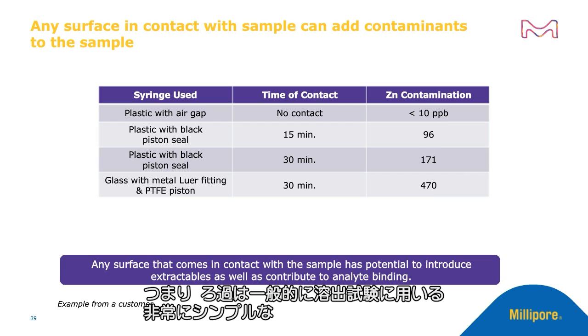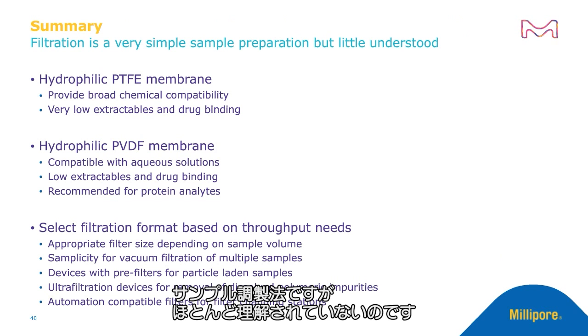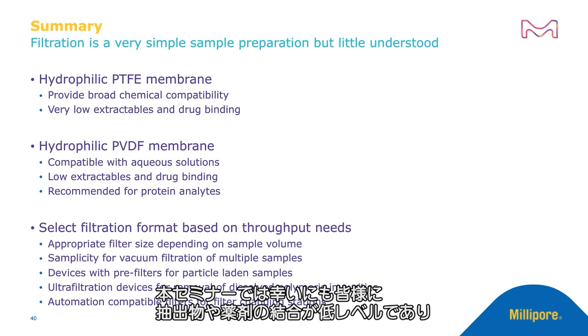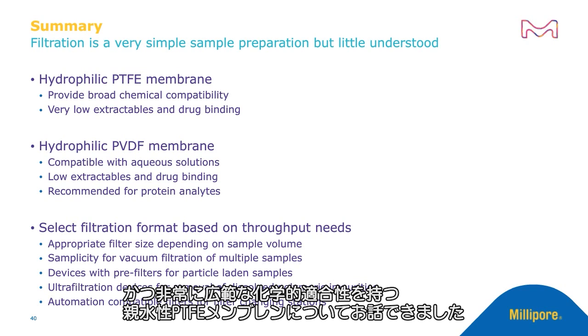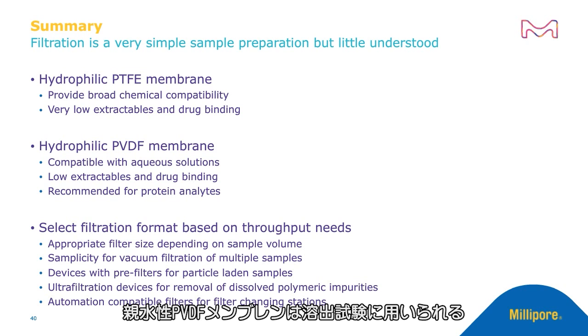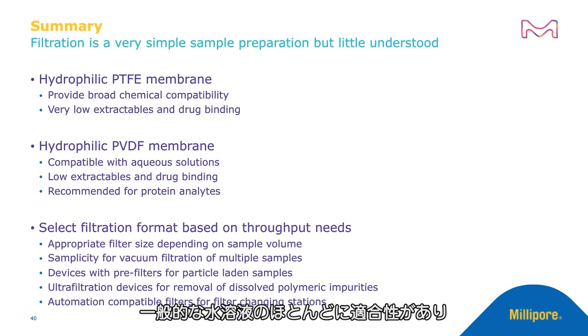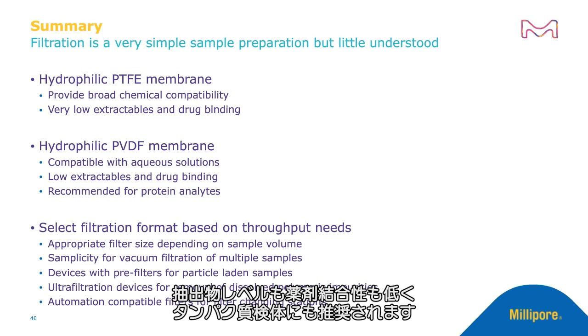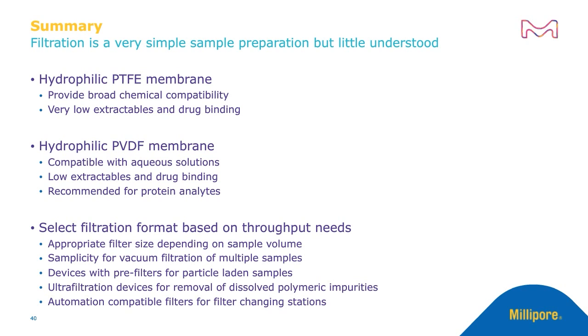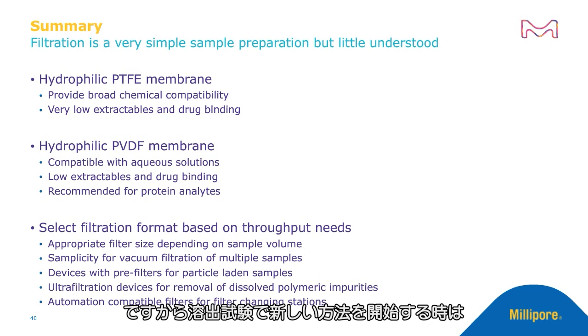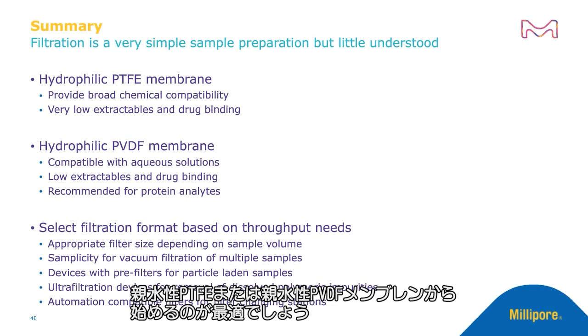So in summary, filtration is a very simple sample preparation technique that is commonly used for dissolution testing, but it is very little understood. In this seminar, hopefully I was able to tell you about the hydrophilic PTFE membrane, which provides very broad chemical compatibility, as well as low extractables and drug binding. Followed by that, hydrophilic PVDF membrane is compatible with most of the aqueous solutions which are commonly used in dissolution testing, also has low extractables and drug binding, and it is recommended for protein analytes. So whenever you are starting a new method of analysis in dissolution testing, starting with hydrophilic PTFE or hydrophilic PVDF membrane would be your best option.